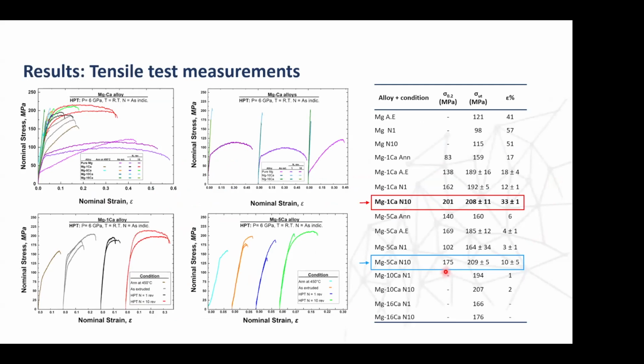Tensile tests we did, and actually, for example, we did get very good behavior, especially magnesium 1 calcium 10 turns. The strength is around 208 megapascals, and ductility is 33%. The way we measure it, it's best to compare between samples, because the samples are relatively small and we don't compensate for machine elongation. So comparatively, we see that this is the best. This is probably not the actual nominal ductility, but what we do see is that it's improved. And also magnesium 5 calcium, for example, 10 turns, is reasonably well behaved as well.